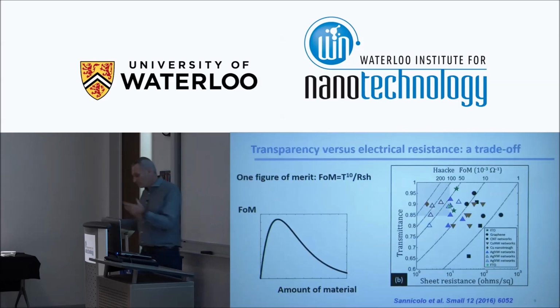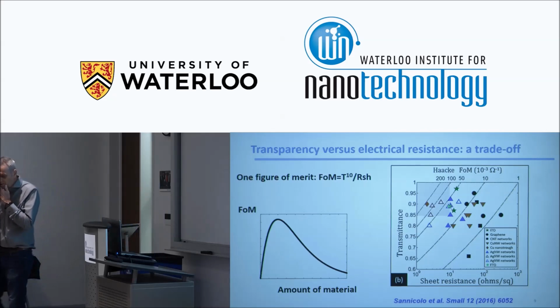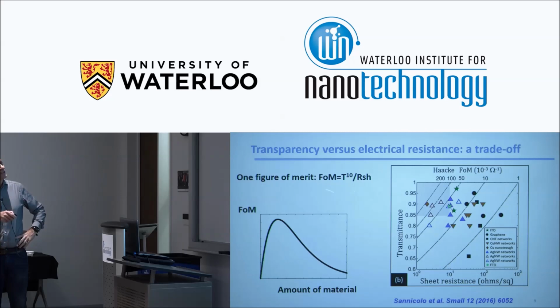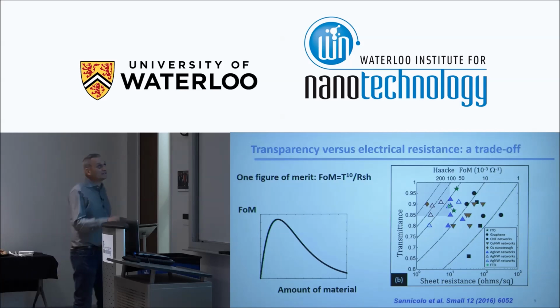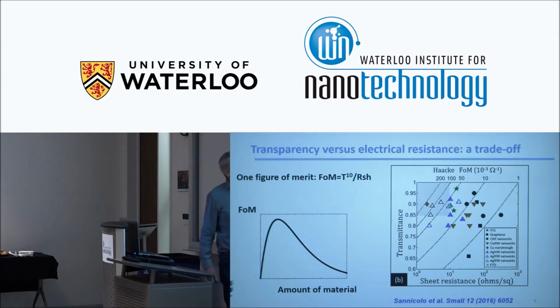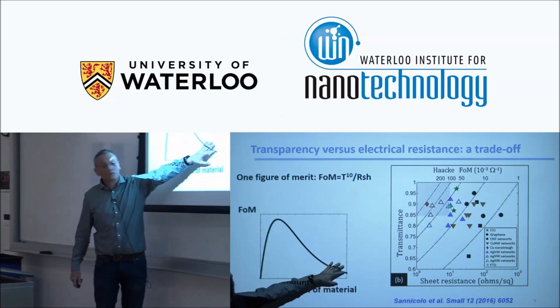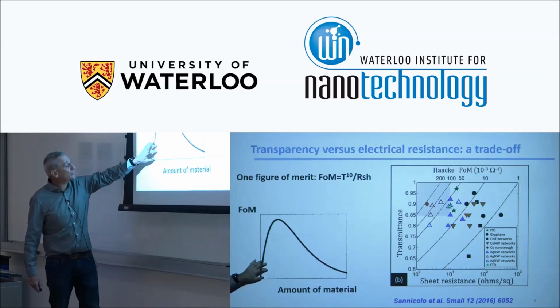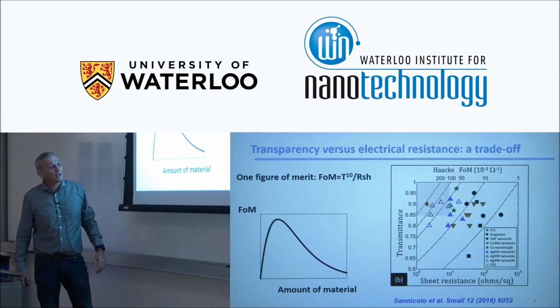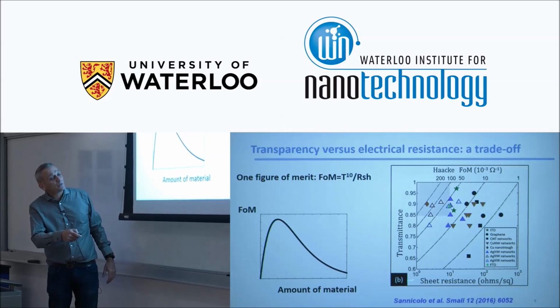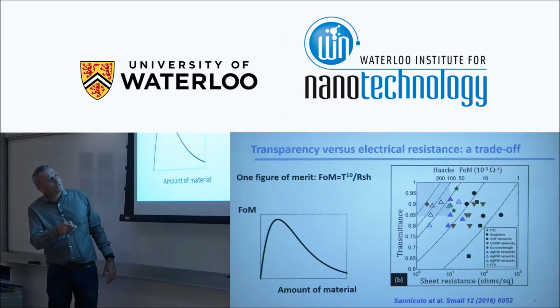So often to quantify this compromise between optical transparency and electrical resistance, we use a figure of merit. The most well-known one was proposed by Haacke in 1976, a long time ago, saying it is the transparency to the power 10 divided by the sheet resistance. We want to be as transparent as possible, so T should be as high as possible, but the sheet resistance should be as small as possible. And if you plot the figure of merit versus the amount of material, you reach a maximum. When we are here, we have put a lot of material. We are very conductive but not very transparent, and here not very conductive but very transparent, and that's a kind of compromise. So what I said before: if you plot transparency versus the sheet resistance in ohm per square, you can have some iso-values of the figure of merit, and the target is somewhere here.